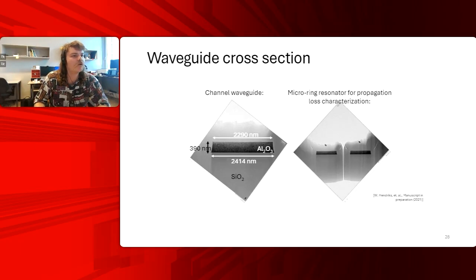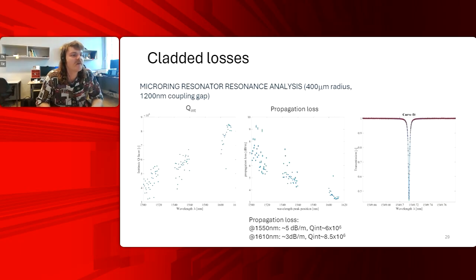A couple of old results here I'll show you of some cross-sectional images of thinner multi-mode waveguides used for ring resonator measurements, which brought us down to these passive results of Qs being in the millions now. So once you're at a million Q, you're good for lasers, which is nice for optical amplifiers as well, because the lower the loss, the better. And you can already see here losses going, based on old ring resonator fits, down to 5 dB, even 3 dB per meter into the L band.